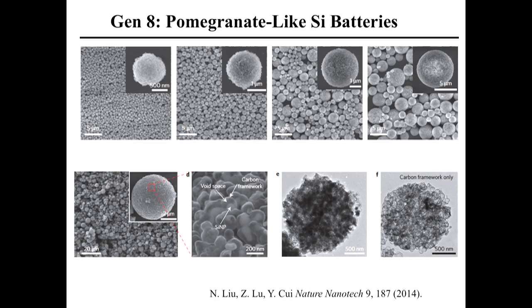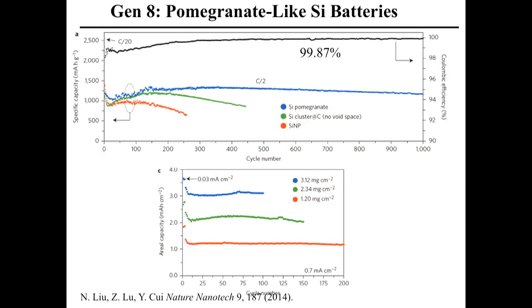So now you use this to build a battery electrode. You do the coating. You put a lot of material onto metallic foil, right? You start to measure its capacity per gram of silicon. You see this is the capacity of silicon, and C/2 is 2-hour charging, discharging speed. It's stable. If you don't have this packing with empty space, this capacity will decay fast.